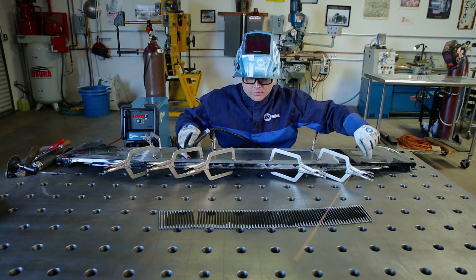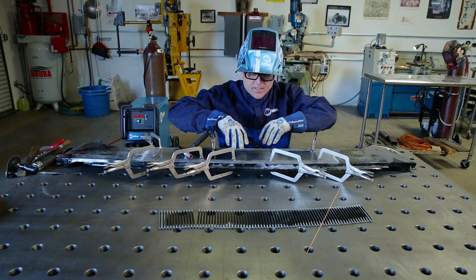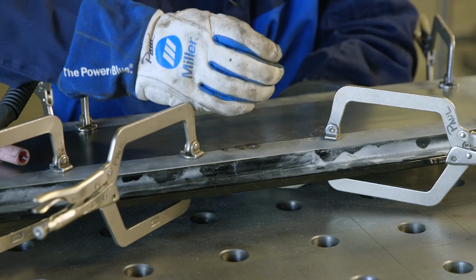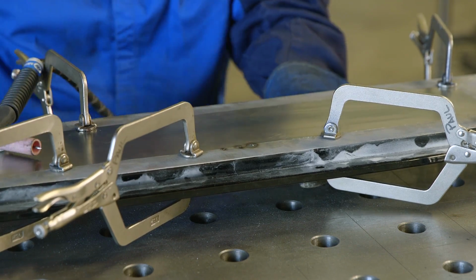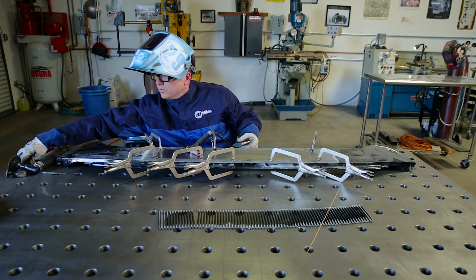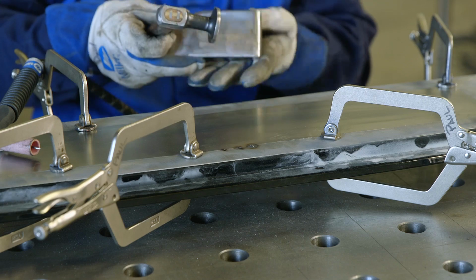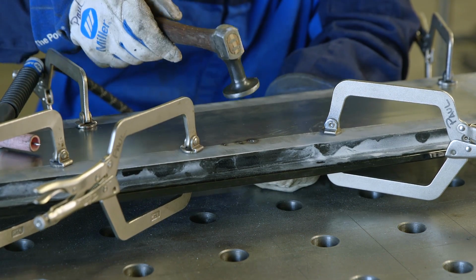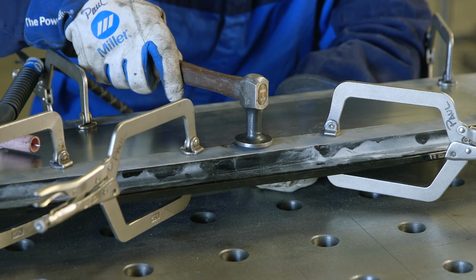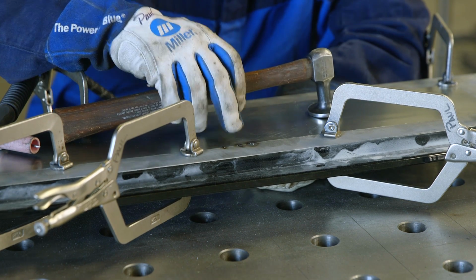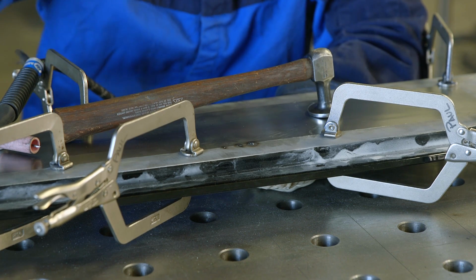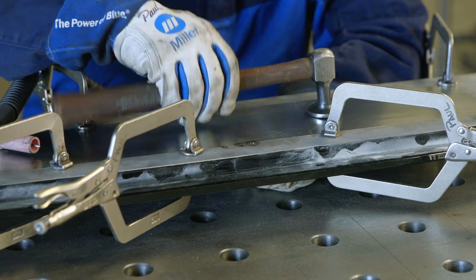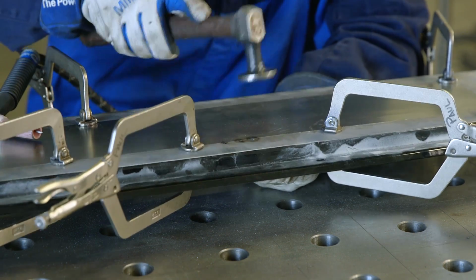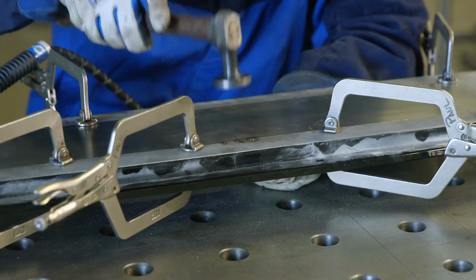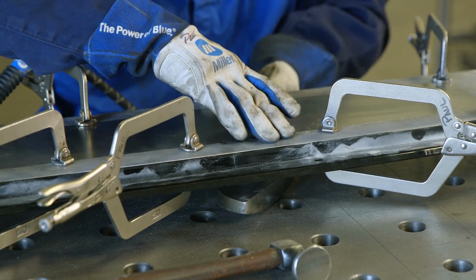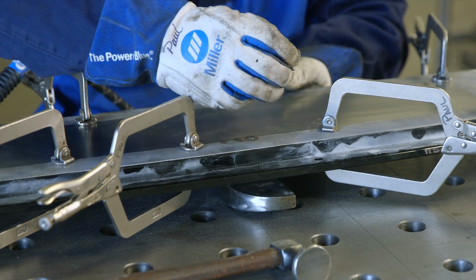One thing that happens while you're tacking is that a lot of times it'll bow up, and like I say, it pulls together. So you want to take, as you go, and hammer your tacks out flat so that it maintains that original shape that you held. And what you're doing, if you hammer this tack, you're actually stretching, you're planishing that tack. So you're stretching it back out to where it used to be. So if you do this as you go, it maintains the flatness, and also it maintains your gap.